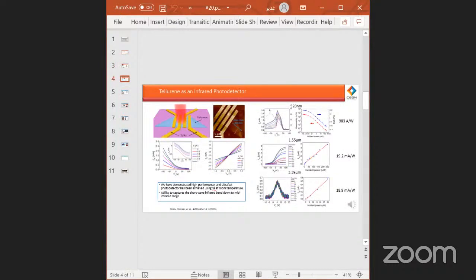Also, our collaborator achieved tellurene photodetectors at room temperature that fully covered the shortwave infrared band with ultra-fast photo response. This free space detector, excited from out of plane and collected from the in plane, presents a peak extrinsic responsivity for different wavelengths. This essentially highlights that its photodetectors exhibit an exceptionally high anisotropic behavior due to Te's unique crystal structure.